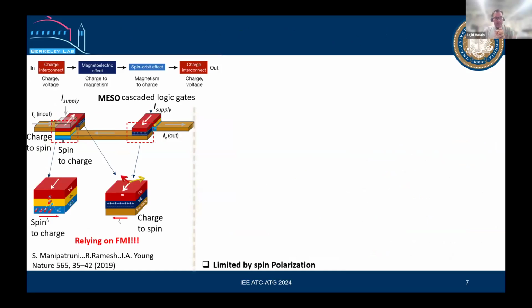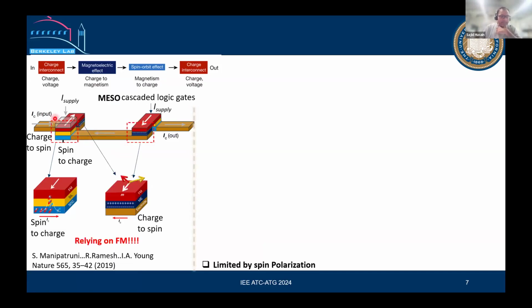So this is a concept, as my title says. The MESO concept means you have some magnetoelectric material coupled with a spin-orbit material. Here, let me bring my laser pointer. Okay. So this is 1 bit, and the other one is a second bit. Using the input current or input voltage, you control this magnetoelectric material, and it is coupled with a ferromagnet. The magnetoelectric is basically an antiferromagnet, and antiferromagnet and ferromagnet are coupled through the exchange interaction. You can use this exchange coupling to manipulate your magnetic material, in red, through the blue, which is the magnetoelectric material. So electrically, you are able to control the magnetic material.